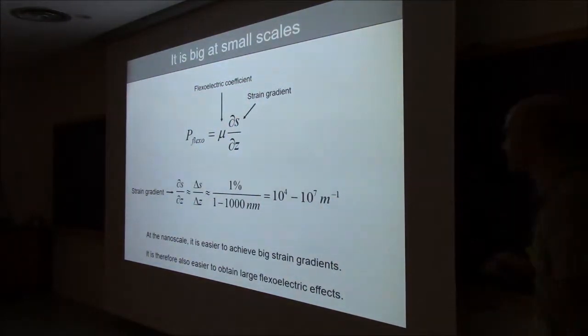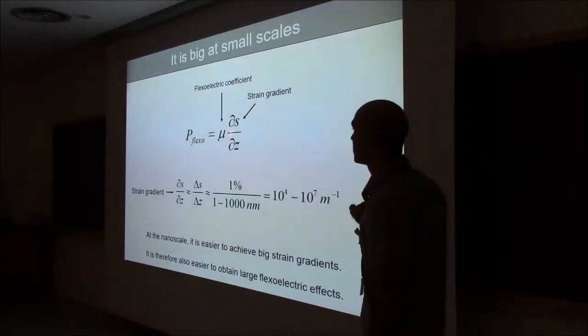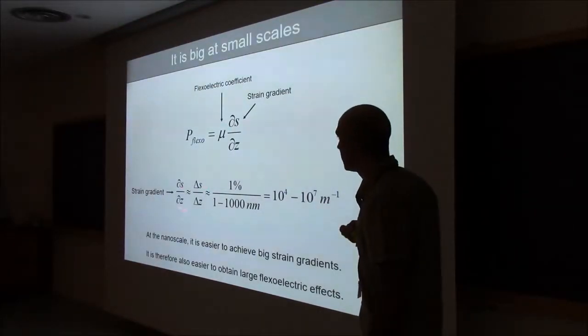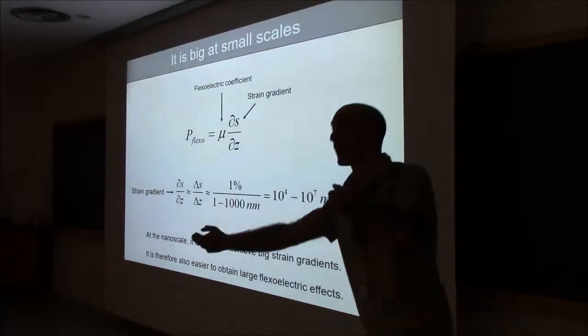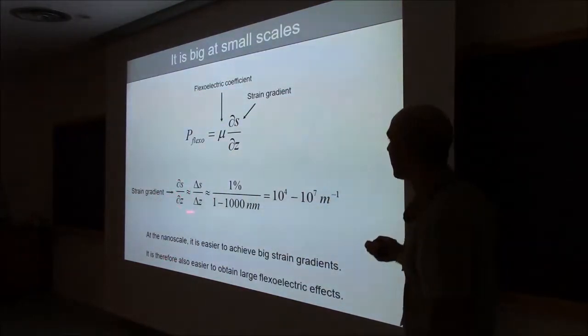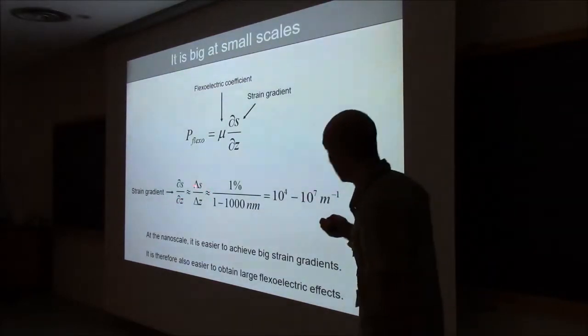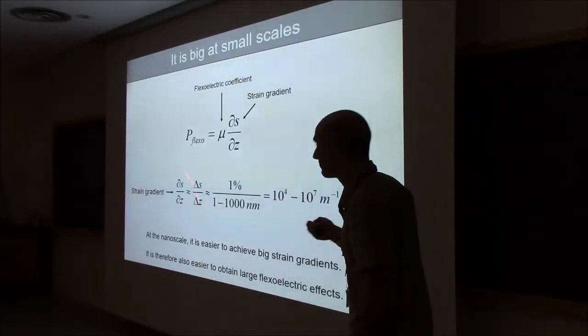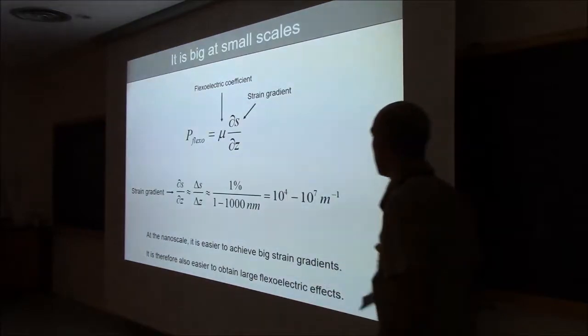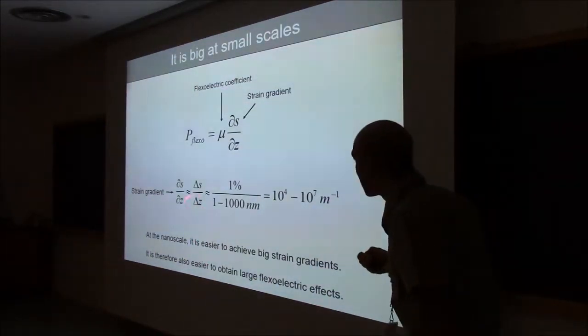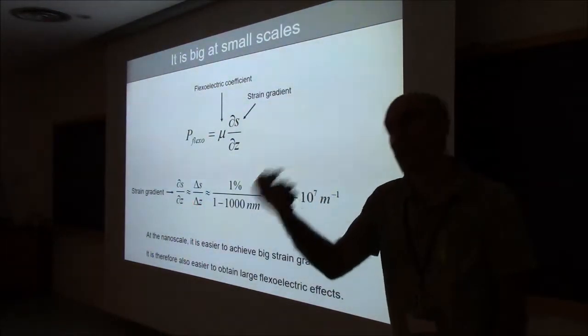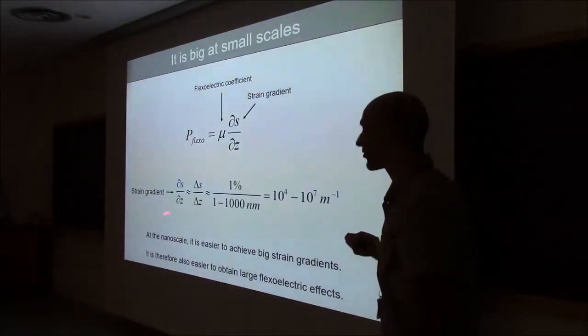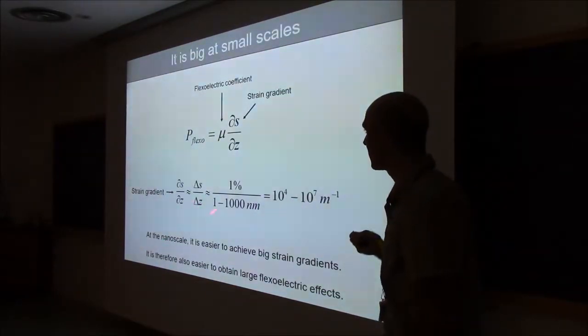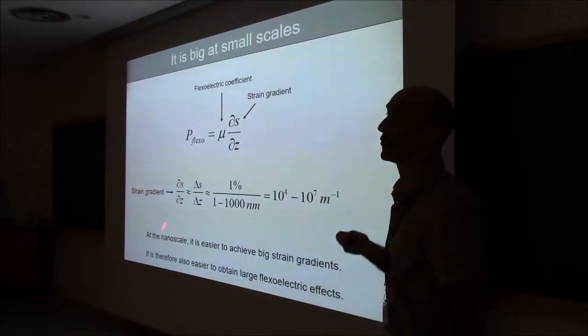Like it's a tensor. But the strain gradient is not. Strain gradient is a strain divided by, well, it's a difference in strain divided by a relaxation length, right? Essentially, this differential, you can approximate it as a difference in strain divided by a difference in position. Since the difference in position or the relaxation length is in the denominator, the smaller you make this, the bigger the strain gradient is going to be.